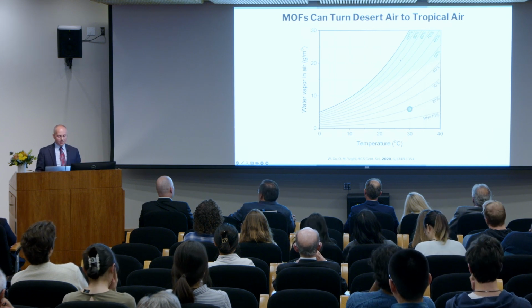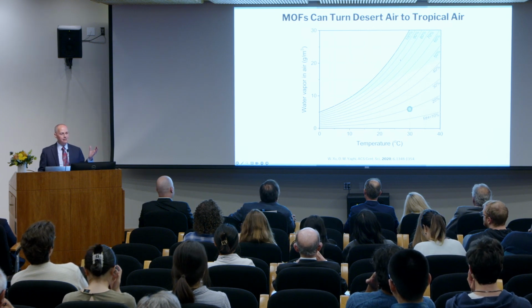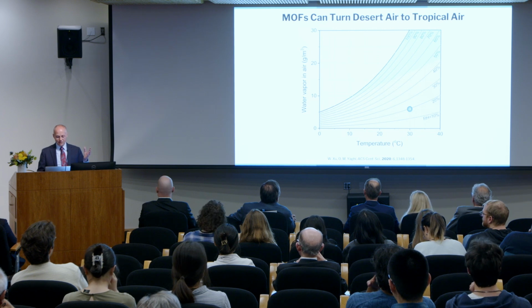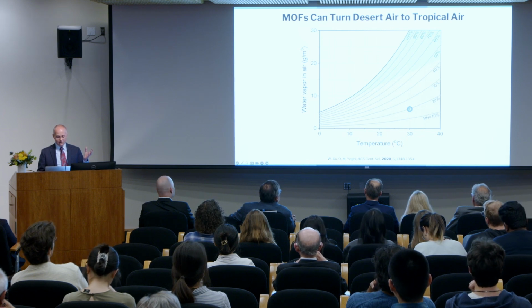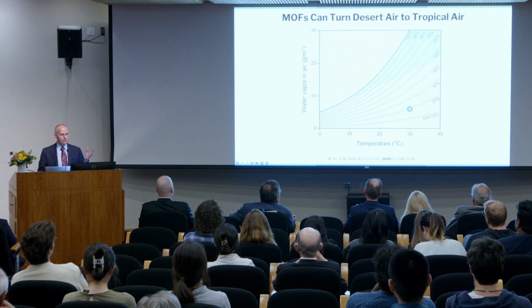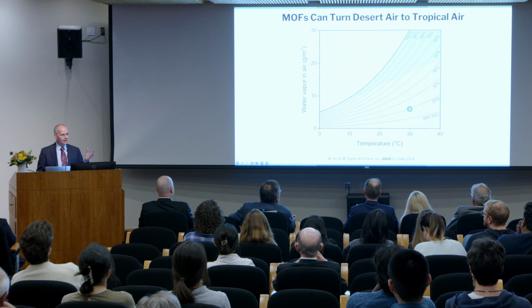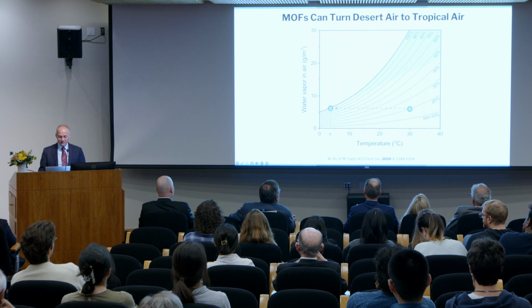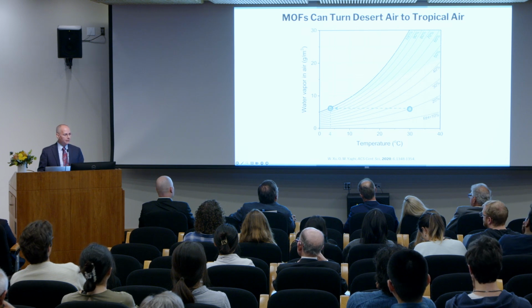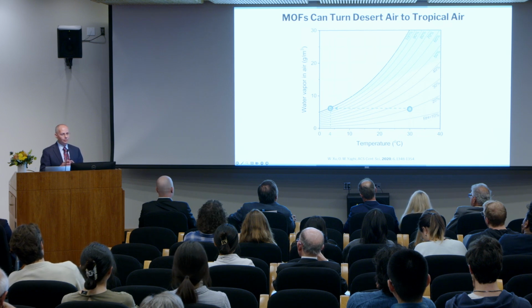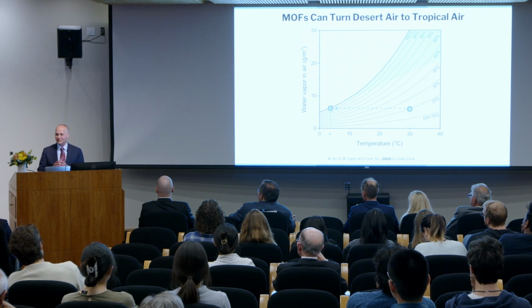But let's imagine that I'm in a city like Granada, Spain, okay? In the summer, I'm at 30 degrees Celsius, and the humidity is as low as 20% relative humidity. And let's say I want to take the water out of that air. I have to cool the air down to 4 degrees Celsius in order to get to 100% humidity and be able to condense that water. Well, that's refrigeration. That's not energy efficient.